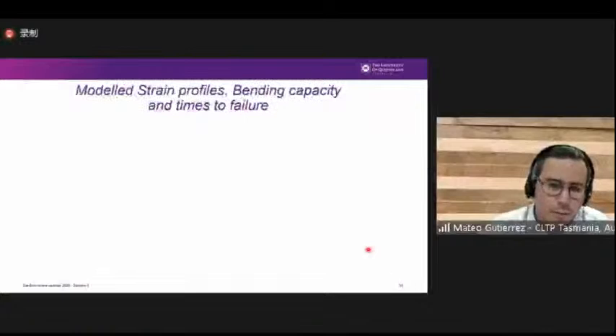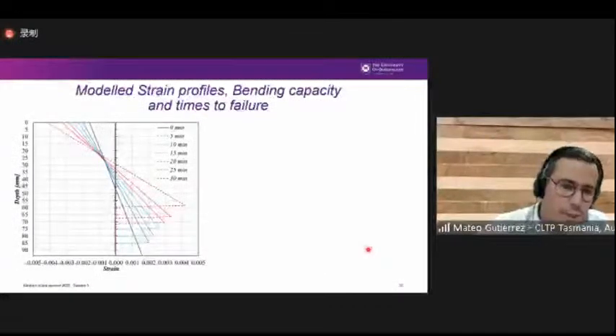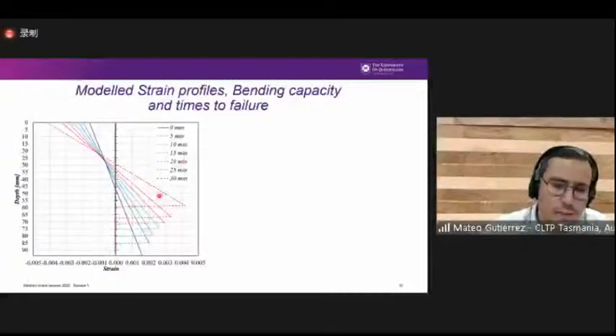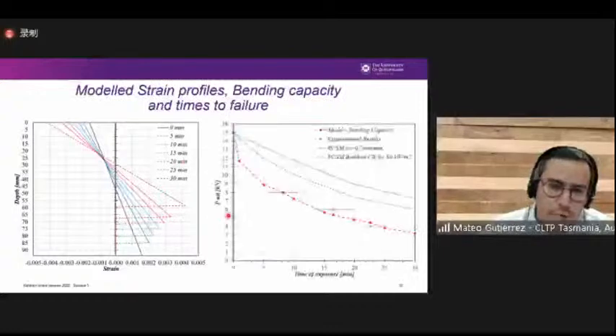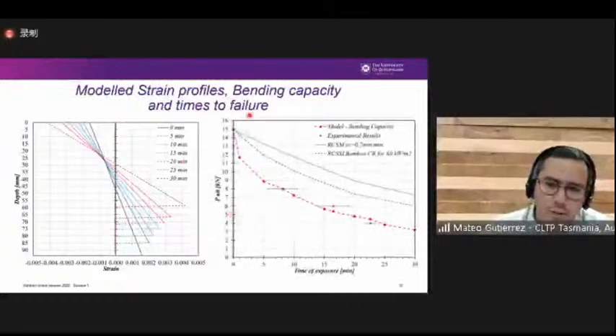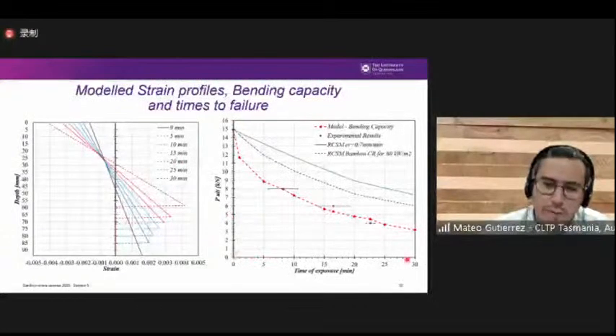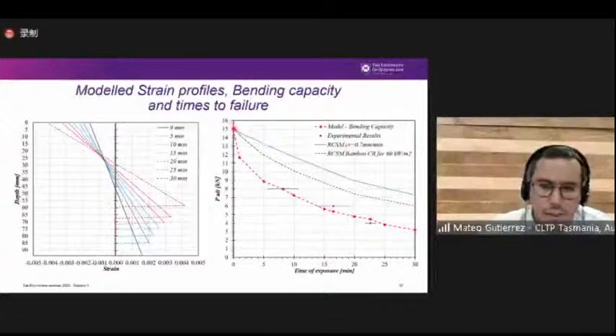So with this model, we were able to predict the strain profiles at all different times of exposure. And we were able to predict the capacity. This is quite an interesting graph, because if you use the reduced cross section method, which is the traditional method that you normally use in timber to calculate the capacity of timber elements exposed to fire, when you normally assume a charring rate, here you will see the reduction in the bending moment capacity against time.